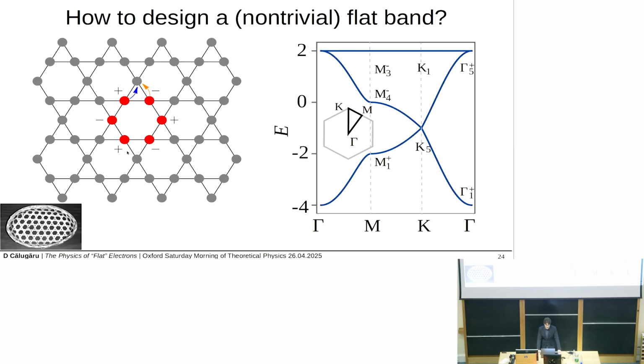But actually what's even more interesting is if you look at this band structure on the right, you see that the flat band actually touches the dispersive bands at one single point in the Brillouin zone. This touching turns out to be protected by symmetry, and you can't gap it without either breaking the symmetries of the lattice or by making the flat band topological. And this is what I really mean by this flat band not admitting exponentially localized symmetric Wannier orbitals.